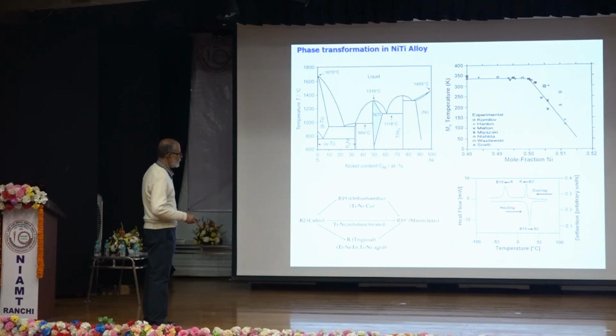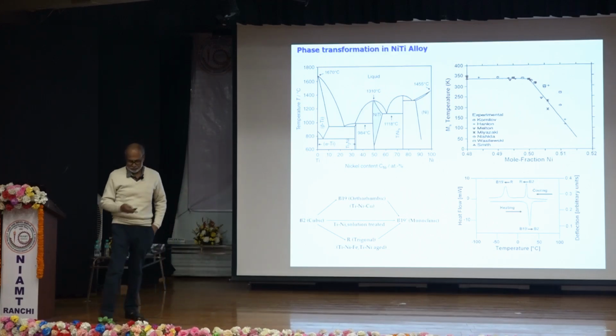So if you heat it, martensite transforms into cubic phase, and when you cool it down, B2 may go to R and R may go to B19', that is martensite. As it happens for epsilon martensite in case of steel. Very often in steel, we get alpha dash through epsilon, gamma to epsilon to alpha dash. So it happens similarly.